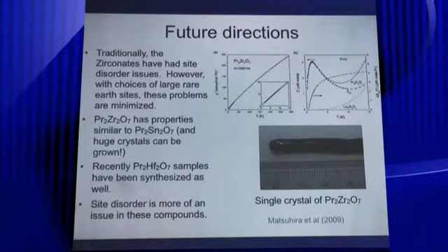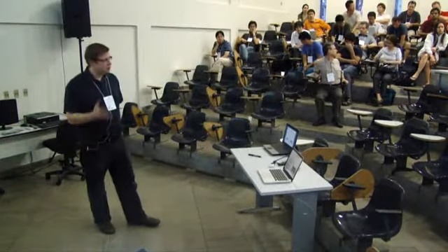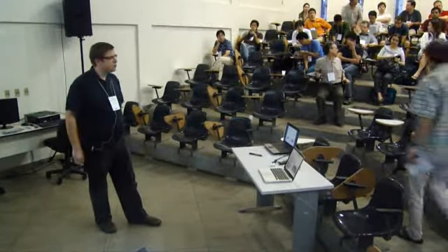So for the praseodymium compound, in terms of synthesis, praseodymium is really prone to have tetravalent valence, right? And so across oxides. So is there any problem here in these compounds? Well, you have to worry about that. There are different types of praseodymium oxides you can start with in the beginning, like praseodymium 6011, for example, and other oxides you can use. Some of them work and some of them don't in the synthesis. So you're right, if you avoid that tetravalent, your reaction will be much cleaner.